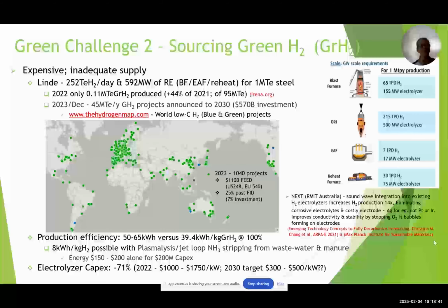The chart here through the hydrogen map shows both the blue and the green projects in the world. And it's a great source to see what's going on. 2023, there were 1,040 projects. And there's a breakdown there of the front-end engineering and the production efficiency is 50 to 65 kilowatt-hours per kilogram of green hydrogen, which is not very good considering the 100% efficiency would be 39.4. There is a new plasmalysis jet loop ammonia stripping from waste water and manure, which could give us 8 kilowatt-hours per kilogram of hydrogen, which would be fantastic.